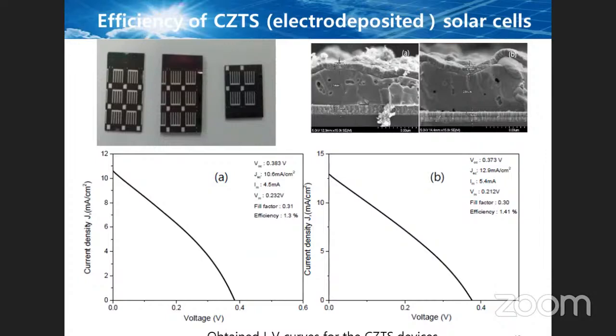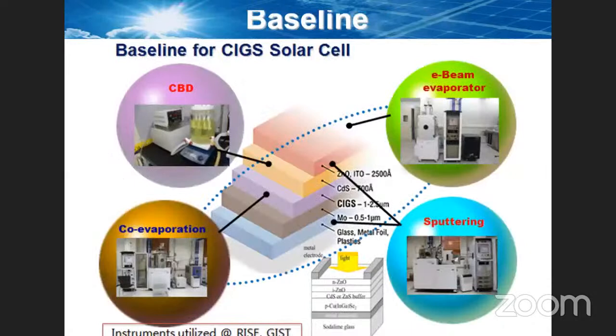Okay, and we obtained the efficiency of the CZTS solar cell, shown in these figures. Next one. Yeah, the same baseline we use for the CIGS solar cell. The device structure is here. We deposited the CIGS by the evaporation method, and then CdS by the CBD, and then zinc oxide by sputtering, and finally the contacts are taken by e-beam evaporation. Next one.